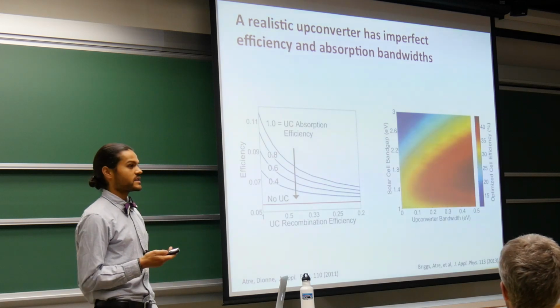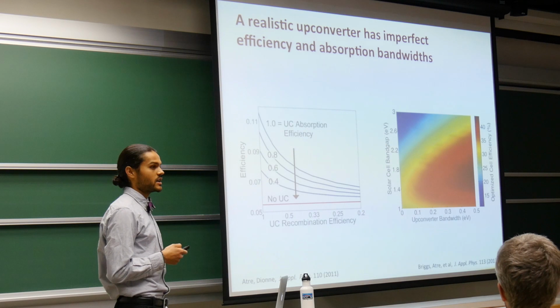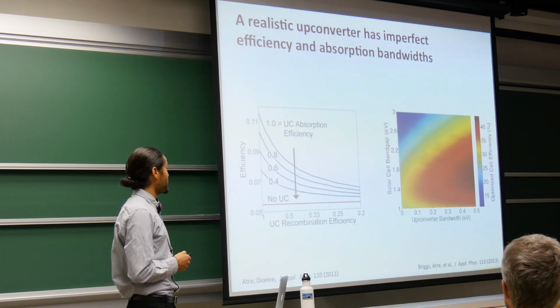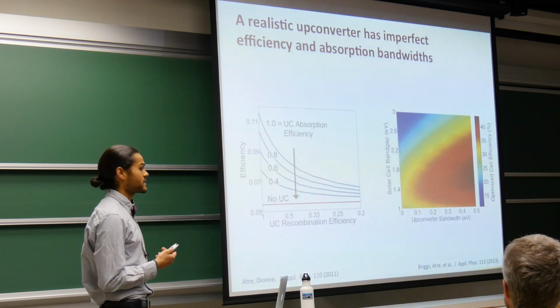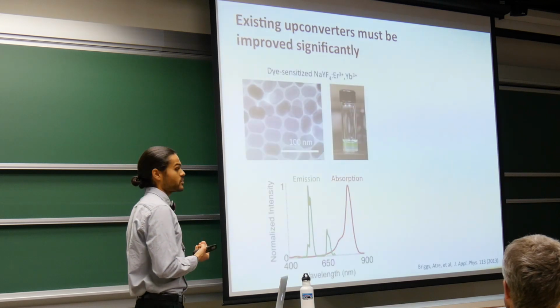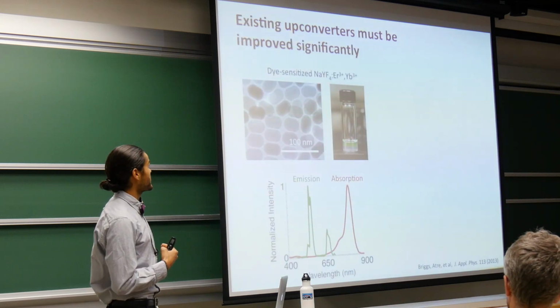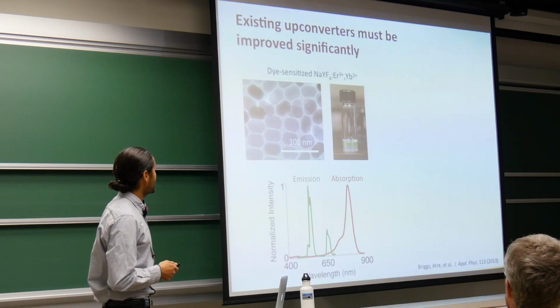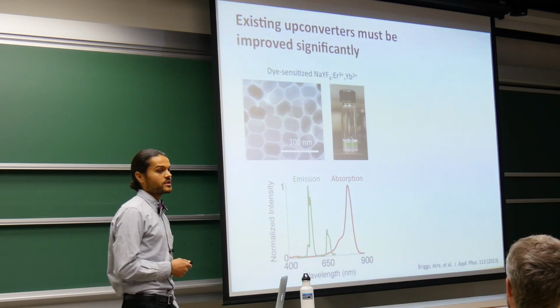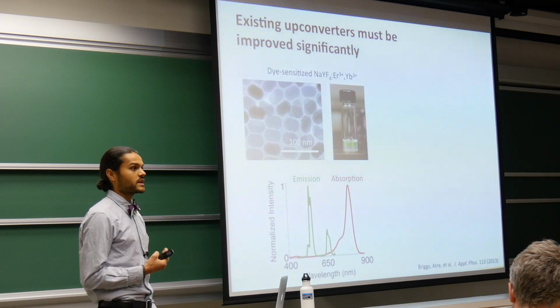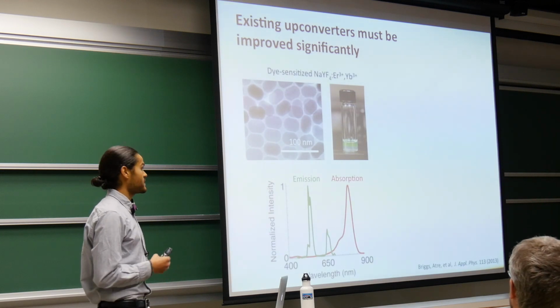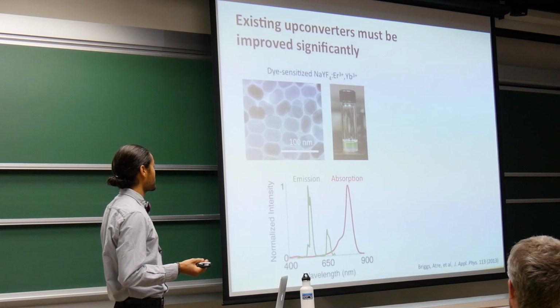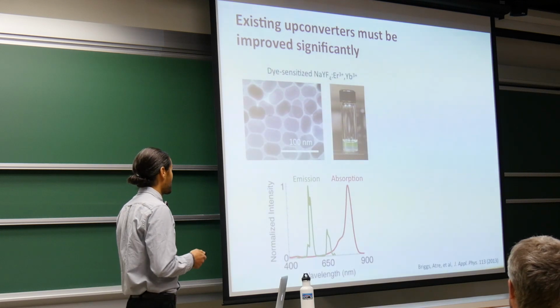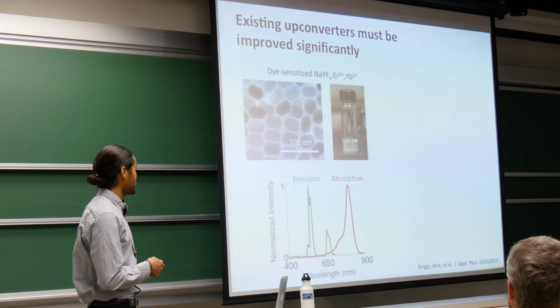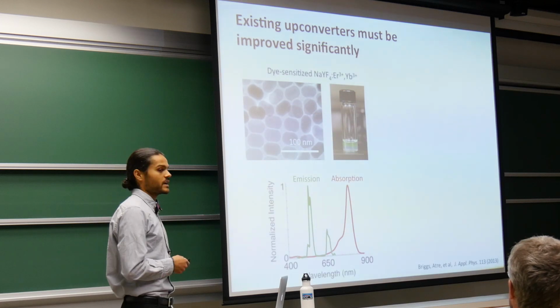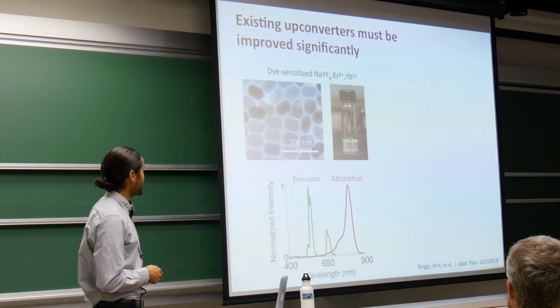So now that we understand how these realistic-like upconverters would behave, let's consider what upconverters actually exist today. Well, one of the most promising upconverting systems is based on lanthanide upconversion. Here we see nanoparticles of sodium yttrium fluoride that have been doped with the lanthanides erbium and ytterbium. And in fact, these particles are also sensitized with a dye to increase their absorption cross-section. But in essence, we absorb near-infrared light around 800 nanometers and emit light in the green, as you can see in the spectrum on the bottom.